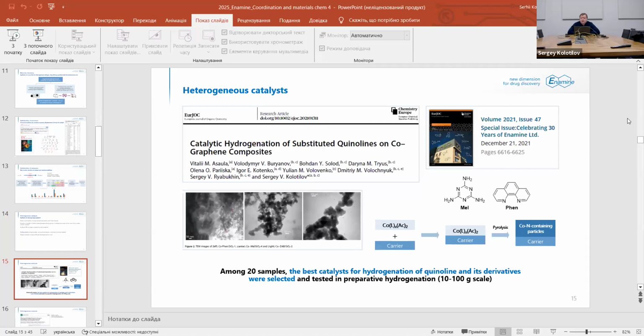One of the examples, we studied a series of cobalt-containing systems for hydrogenation of heterocyclic compounds. These systems were formed by pyrolysis of cobalt complexes deposited on different carriers. And among the systems which we synthesized, we found the best one suitable for hydrogenation of heterocycles. And we use them for hydrogenation of quinoline and substituted quinolines in a scale up to 100 grams.